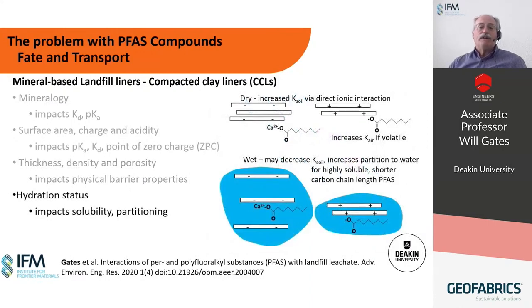So a final important consideration for mineral systems is their hydration status. Saturated conditions tend to promote the presence of PFAS in the water column and preclude its presence in the interfaces, at least the interfaces with the mineral phases. Unsaturated conditions do promote those interactions with the interfaces. So water-mineral, air-water, and air-mineral interfaces will become important for PFAS partitioning. However, the jury's still out in terms of how that is actually interacting and controlling PFAS migration.